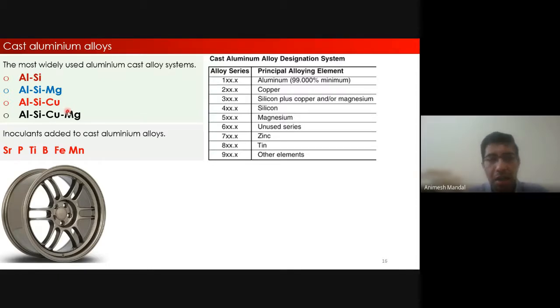That's very commonly used. The reason being, if you add magnesium and copper or both, you make that alloy a precipitation hardenable alloy. Aluminum silicon alloy by itself is not a precipitation hardenable alloy, but the moment you add magnesium, it will generate particles called Mg2Si, and you can create precipitates of Mg2Si. Similarly, if you add copper, as we know, you can create precipitates of Al2Cu. Likewise, if you add both, you can have different kinds of precipitates.